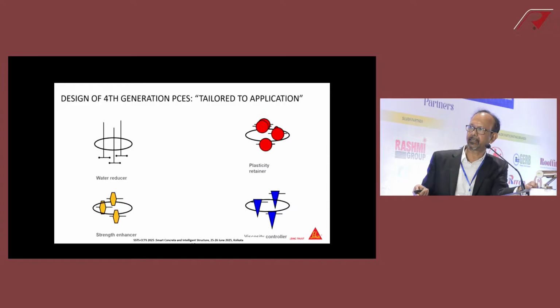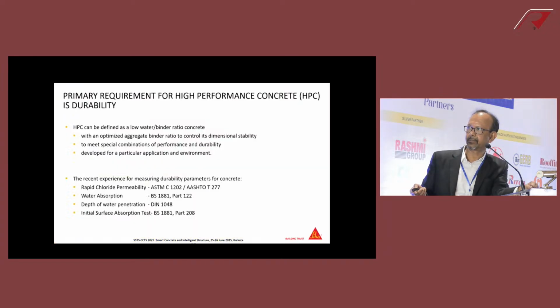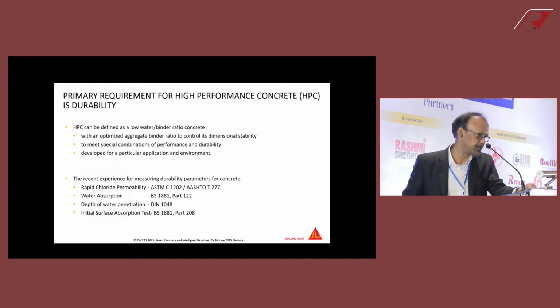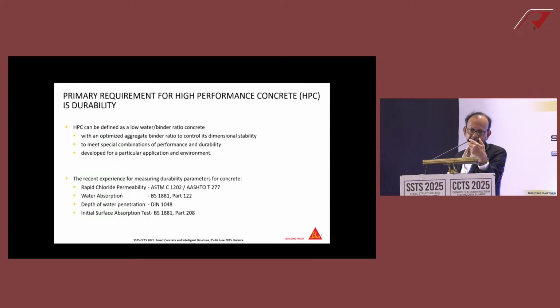Long chain, short chain. So just to give you another picture. High performance is basically about the low water binder ratio. And for that, we need to have special, tailor-made additives or admixture. And I mentioned about durability. So you can see RCPT, water absorption depth, and initial surface absorption. 4 main parameters. Considering exposure is extreme or severe, how close it is to the saline conditions or sulfate conditions. Chloride attack is obviously faster than sulfate attack.